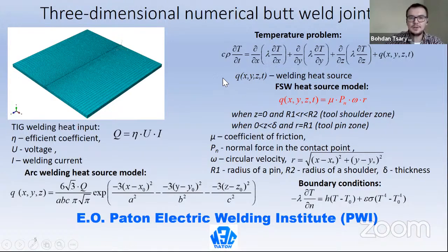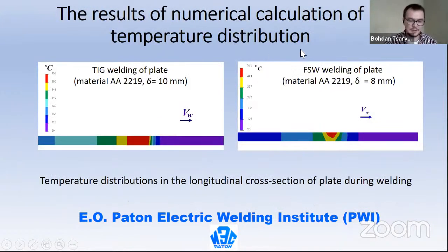Here is represented the model of the temperature problem, heat. Here we have the heat source for FSW and for arc welding. For friction stir welding, we use a heat source equal to the coefficient of friction multiplied by the normal force in the contact point and the circle velocity, and then multiplied by the radius.